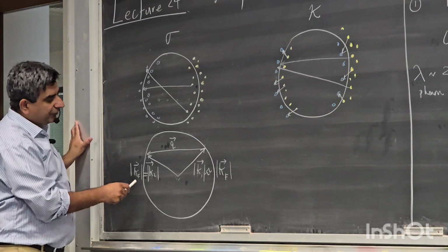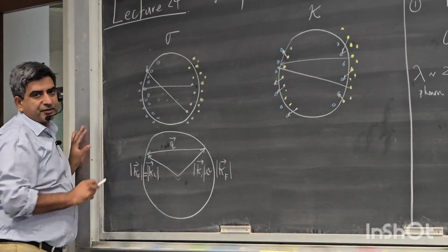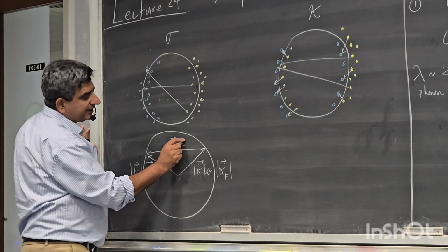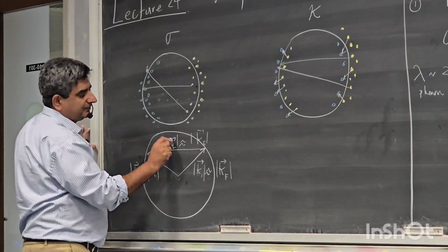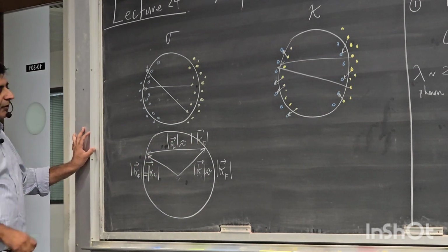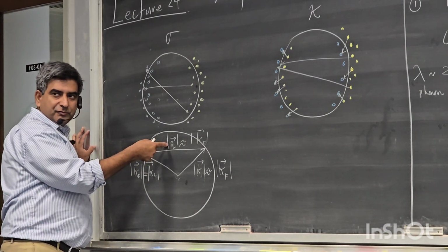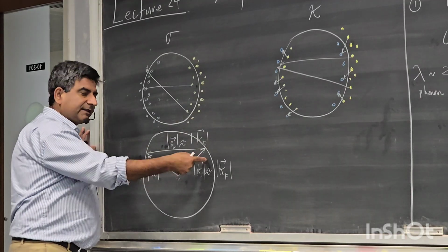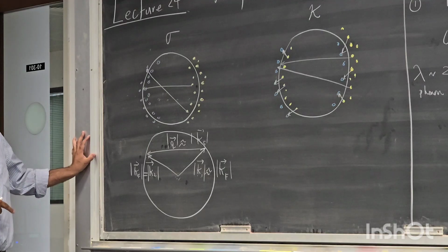Okay, so if you look at this geometry, this wave vector q should also roughly be the same as kF. Suppose this is an equilateral triangle. So if phonons of this wave vector q comparable to the Fermi wave vector are available, then this process is an efficient process. This process will happen.